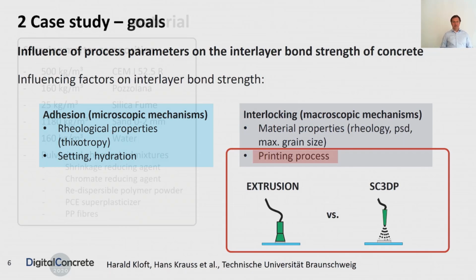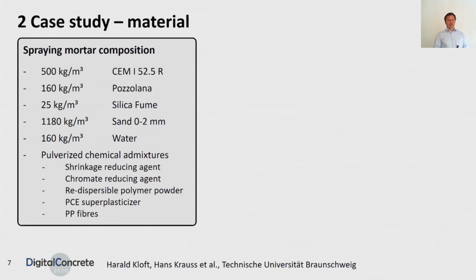Today we'd like to analyze the influence of process parameters in the case of extrusion and of shotcrete 3D printing. The material we used was a spraying mortar available on the market. You see here the mortar composition. It is quite a complex material with a lot of chemical mixtures contained in pulverized form. Here too, I don't want to go into details.